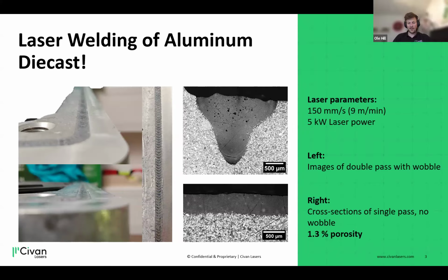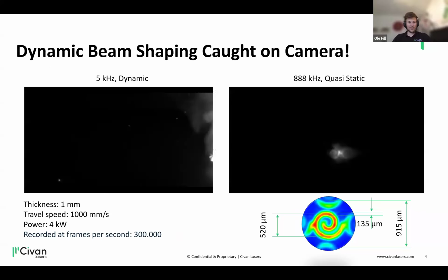And you also can see on the right the laser parameters, or at least the rough edge of the laser parameters, and you see we're welding at almost 10 meters per minute here. If you compare it to something like friction stir welding, you're on the magnitudes of 20, 30 times faster. But I will get into the details later in the talk.